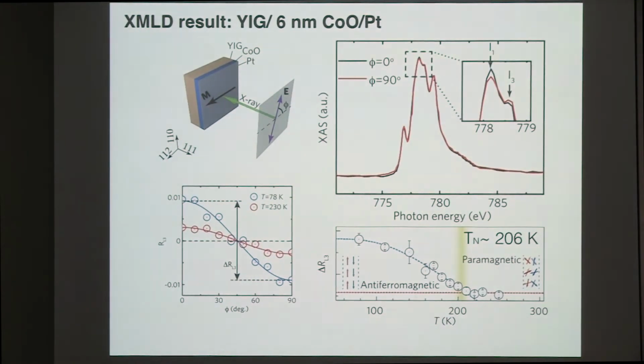So the final thing we need is to tell whether it's really the Néel temperature or not, because so far we can only speculate that it's maybe the Néel temperature, since everything looks like Néel temperature behavior. We need very hardcore evidence to pin this down. So to do this, we went to XMLD at UC Berkeley. In the experiment, we can directly use X-ray linearly polarized light to illuminate our sample and try to get this XMLD contrast.